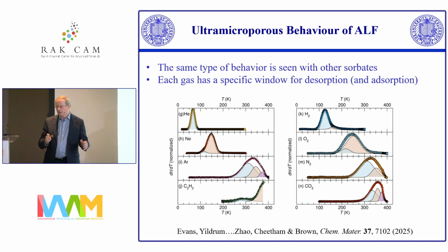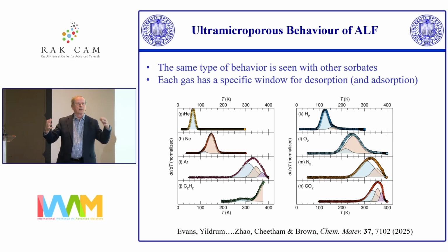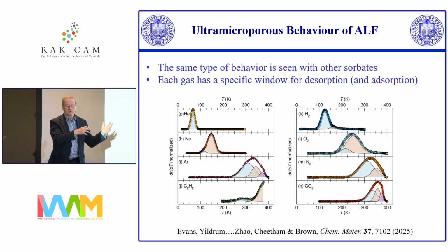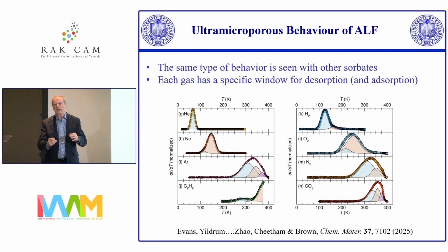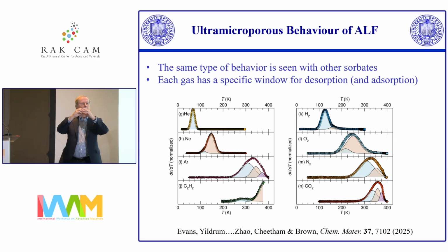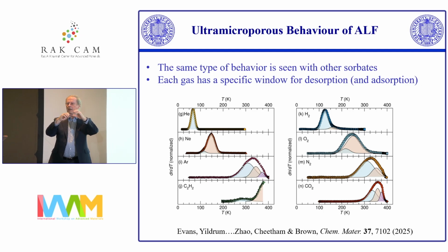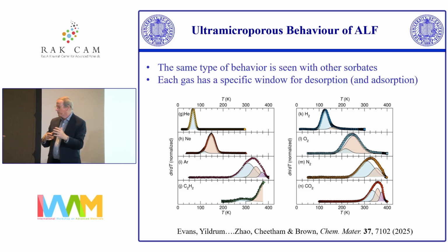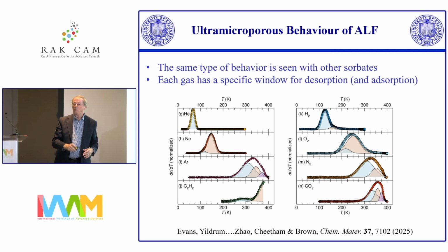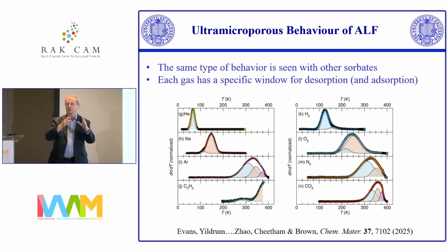So the reason for this is that the ALF is very dynamical. It's not a rigid framework like I've shown you. It's a quite dynamic framework. And as you warm it up, the windows into the cavity where the hydrogens are from the formates, they just sort of expand. The windows get bigger, and so you get to the point where larger and larger molecules will go through, or molecules that are interacting with the formates in the ring.